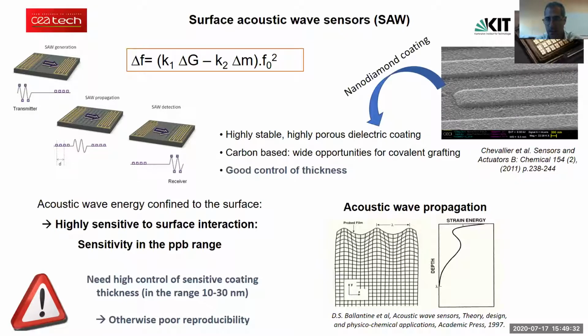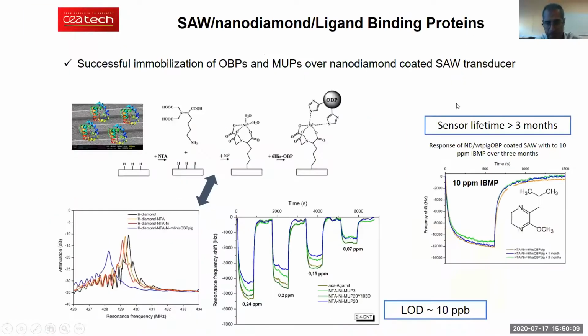This is why we developed this coating based on nanodiamond. We are depositing nanodiamond particles across the surface of our surface acoustic wave sensors. What you can see here are the gold IDT electrodes, which have been conformably coated with these diamond nanoparticles. What we get at the end is a carbon surface, which is highly stable because it's diamond. It's made of nanoparticles, so we have a very high surface area, so we can make a very sensitive sensor. We can also use this carbon surface to immobilize proteins on the surface of these sensors. So this is what we did.